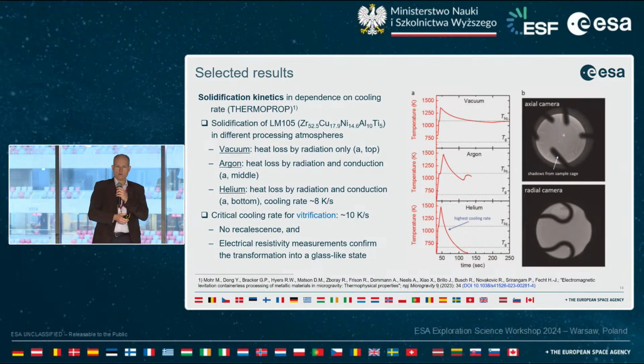So you can use vacuum, where you have radiative cooling. It's relatively slow. And you can use a gas environment, so you can go from argon to helium. Then you couple, of course, with the cooling to the gas, and you see for helium the cooling rates are much faster. And then you can see what impact this has on the solidification kinetics.